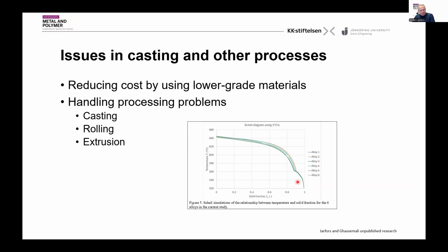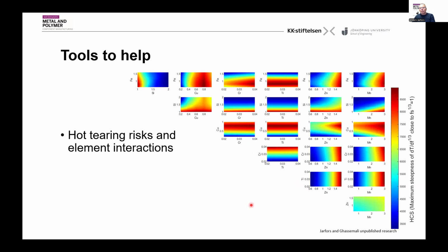And if you take the next slide, this is an example where we've been calculating the hot tearing index of the materials as a function of different compositions. This is a plot that we've done, and we used Thermo-Calc and the Scheil equations here, and we are working on our own model in order to produce this. We've been doing 500,000 of these Scheil calculations, trying to show how the various elements are, so to say, behaving in this system.